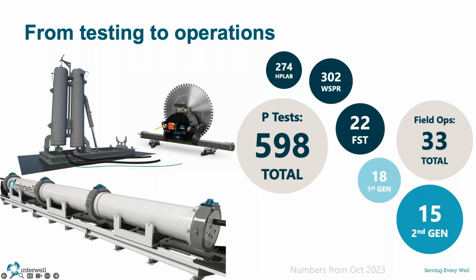including the casing. We cement that inside of a caprock analog. During the test, we're able to run that test, and with a custom-made saw, one of which you can see in the picture here, we're able to evaluate the barrier immediately after that test by cutting it open. We do that one day after the test has occurred. To date, we have run over 800 tests, 600 of them being pressurized. So that 598 total is pressurized tests itself.